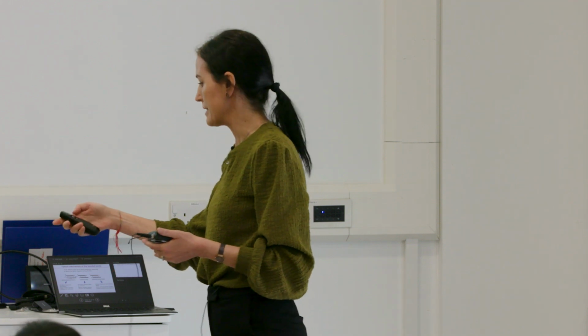The second one is the cohesive failure mechanism, where the failure happens here within the adhesive. And this, of course, is related to strong interfaces between both of them, or stronger relative to the first situation. And then we have this third situation where both failure mechanisms coexist in the same sample. So in some regions, we'll see that it is the cohesive failure mechanism the one dominating the system, and in other regions, it will be the other one. So what's happening in our samples?